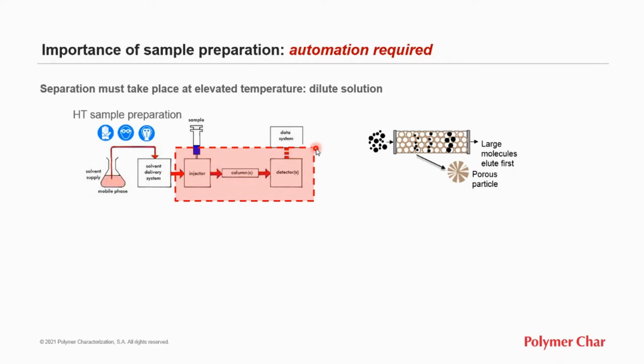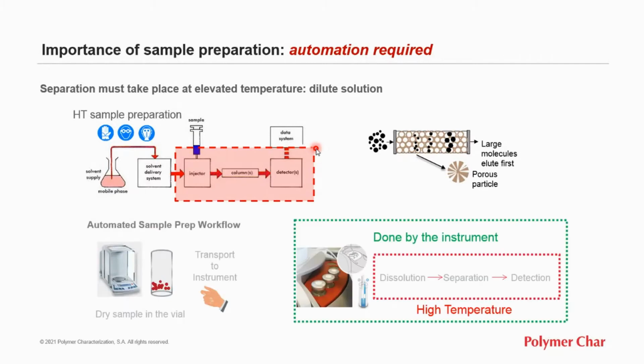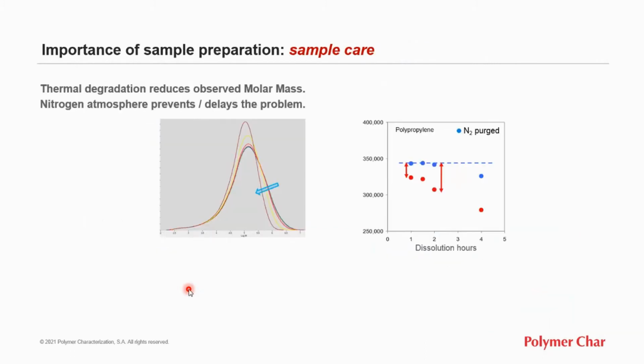In addition, there are also analytical concerns due to the possible partial precipitation of samples, cold spots, lack of reproducibility, and so on. So automation of all the analytical process is highly desired, including the sample preparation. The analyst should only put the polymer dry in a vial and then bring those vials to the instrument. Then the solvent addition, dissolution, filtration, and separation detection at high temperature is done by the instrument with full safety. Automation of all those steps make a big difference in efficiency and also in reducing the analyst risks.